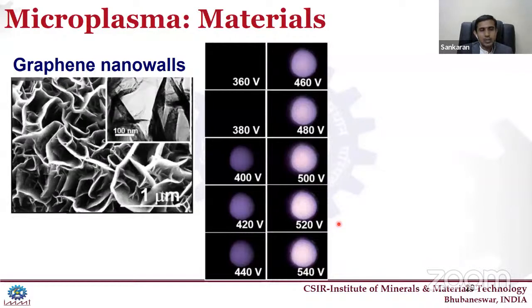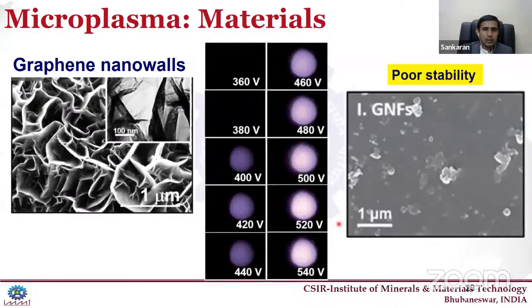So what we did was use graphene nanowalls with a thickness of 1 micron, and even though it has very poor stability, you can see it has a breakdown voltage of 400 volt. Plasma emission is okay up to 540 volt, but the graphene nanoflakes are completely etched out by the plasma within like 30 minutes of electron emission. So we need a high electron emission material which can withstand the plasma for a longer time.